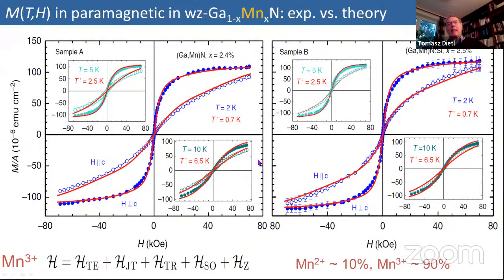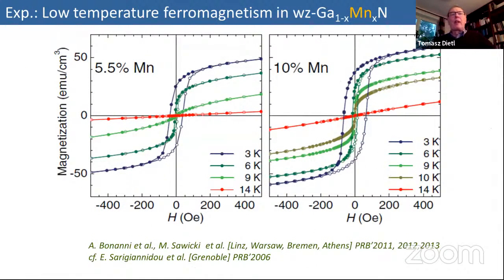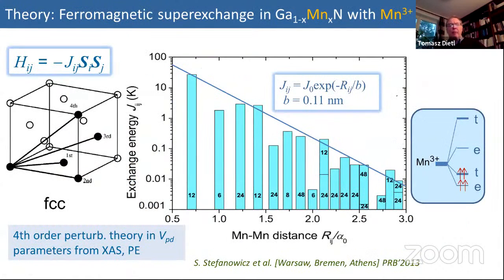But if we increase manganese concentration, what we start to see is ferromagnetism. There is some ferromagnetic coupling, and the temperature is not very high. You see a few K maybe, but still it is quite interesting what is the origin of this ferromagnetism, mainly in gallium manganese nitride. And knowing a lot about the system, we can do, basically with no fitting